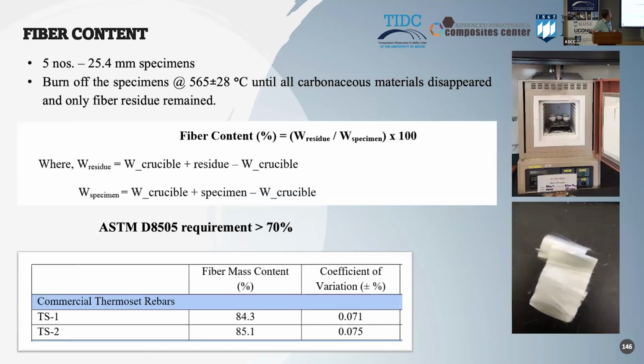Next one. Now, fiber content, how much reinforcement is actually there? And to do this, we do a burn-off test. We do a test where basically we burn off the polymer, the residue will be the fibers, and then based on that, we can compute the weight of the fibers.